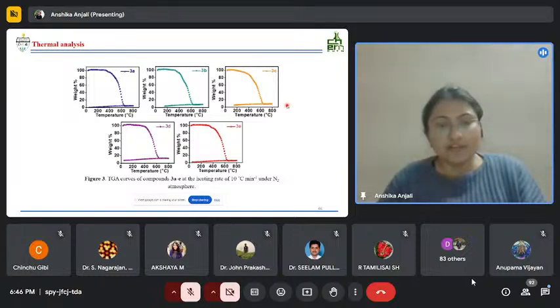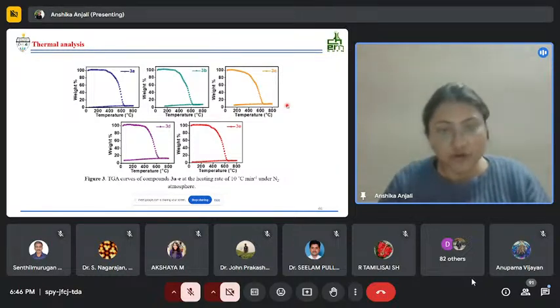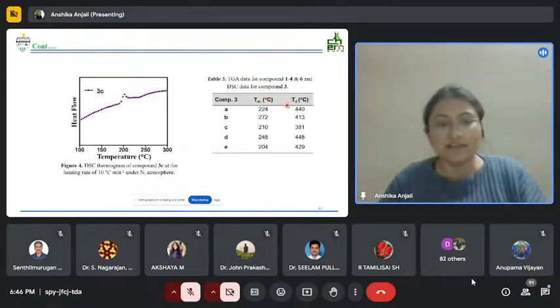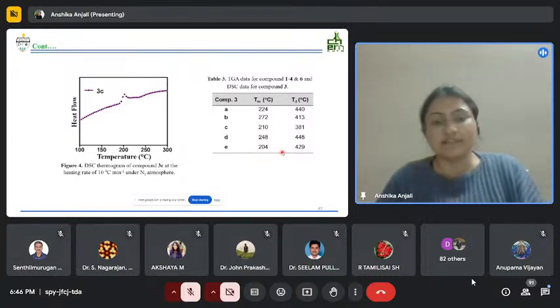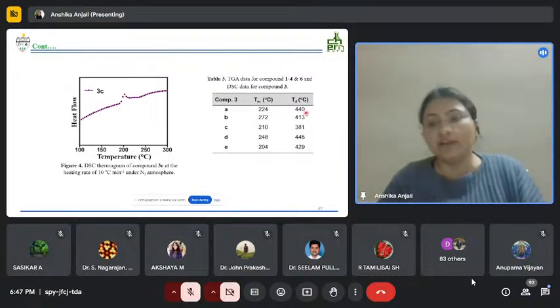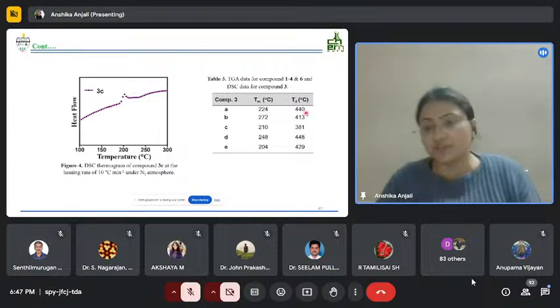So we have recorded the TGA, the thermal gravimetric analysis, and we have DSC thermograms as well. These compounds are thermally stable as they have a melting point higher than 204 degrees Celsius and a decomposition temperature over 381 degrees Celsius. When comparing this compound to the previous one, almost a 94 degree increase in melting point was observed, and almost a 100 degree increase in decomposition temperature was observed.